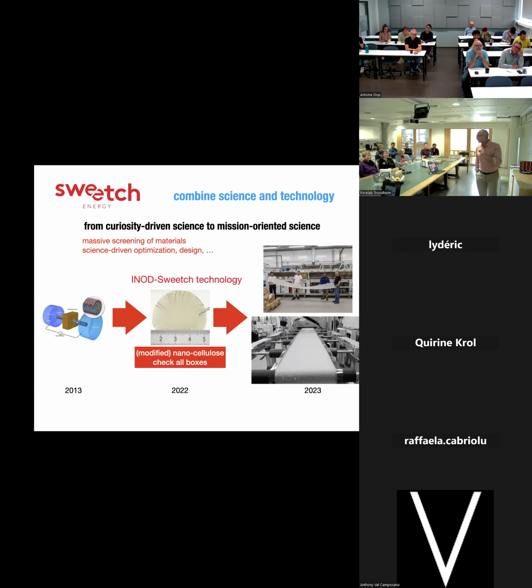And so what we did, that was 10 years ago, we co-founded a startup with some guys who were a bit crazy to believe us. And they did incredible work. We first worked together to screen materials. And at the end of the day, they explored many materials, but one which is very interesting is a modified cellulose. It's a nanocellulose, so it's a specific recipe, but it's cellulose, so it's paper.